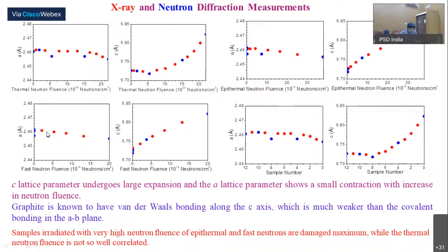The C lattice parameter shows large expansion, and A does not show any change. This is because along C, between two layers, there is van der Waals bonding, which is a weaker bonding. Because of the weaker bonding along C, there is an increase in C, and in the AB plane the bonding is covalent, so it shows only a very slight decrease, and the effect is not very significant. We also conclude from here that the samples which have seen very high fluence of epithermal or fast neutrons are damaged the most. You can see that these 4-5 samples do not show any change with the fluence.